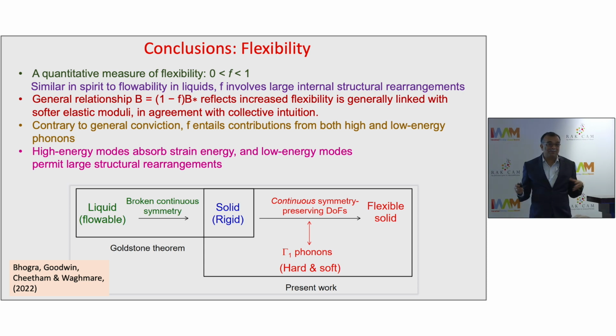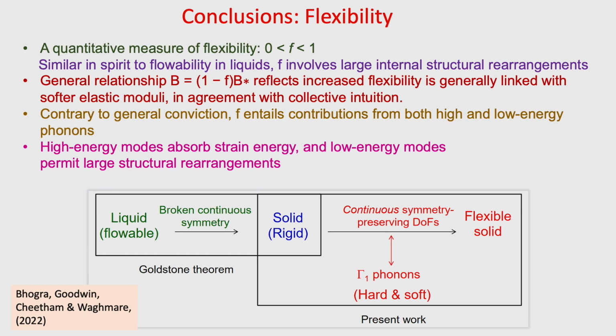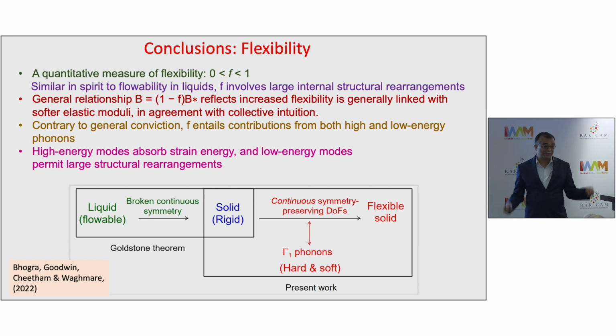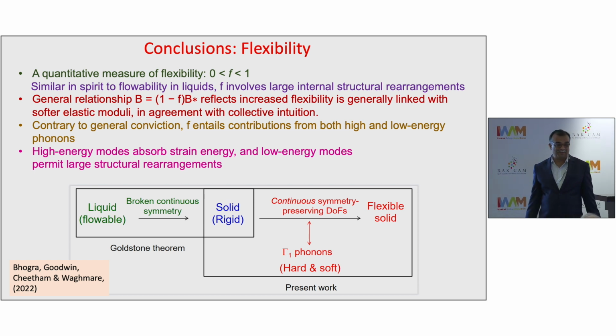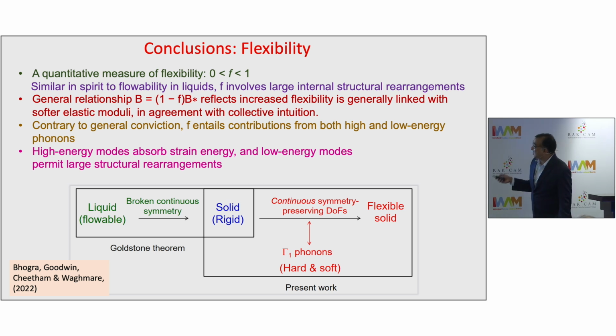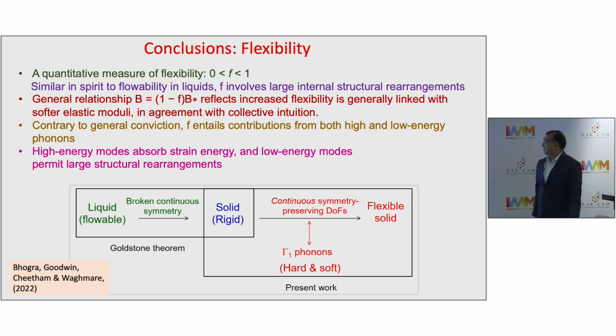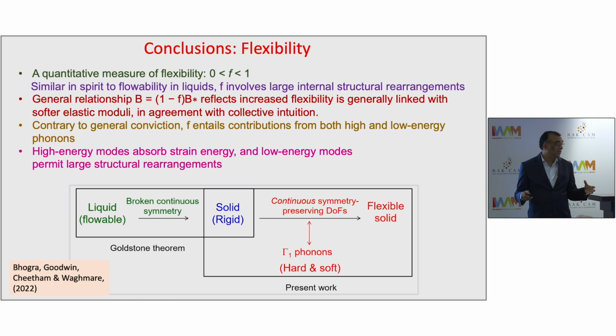So let me conclude the first part of this talk about flexibility. So we proposed a quantitative measure of flexibility which goes from 0 to 1 for crystalline systems. It's similar in spirit to flowability of a liquid. The general relationship reflects that increased flexibility is linked with softer elastic moduli, which is consistent with what Tony's group had published earlier. Contrary to general conviction, it entails contributions from both high and low frequency vibrations, and high energy modes absorb the energy and stresses, and soft modes basically give you large deformations. That's the picture which comes out.